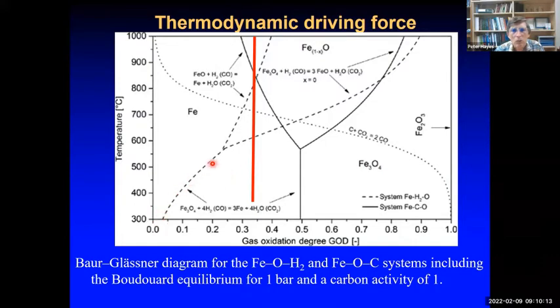So you see that as we go up in temperature, the equilibrium between iron and FeO, that is the critical condition for reduction, changes with temperature. And similarly, we can look at this full line here. This represents the line for the CO-CO2 system. At low temperatures, we see that the equilibrium between iron and, in this case, magnetite is almost constant with temperature. It doesn't change very much until we get up to this triple point here. And then we see the reaction requiring more CO in order to reduce the iron oxide.